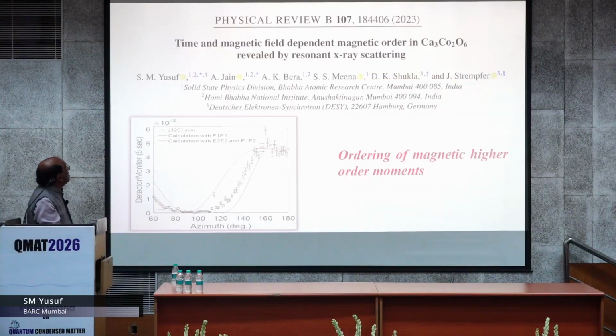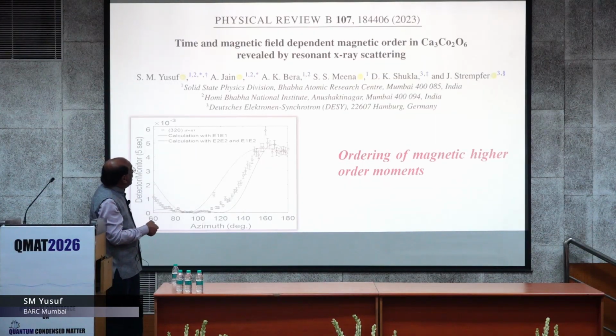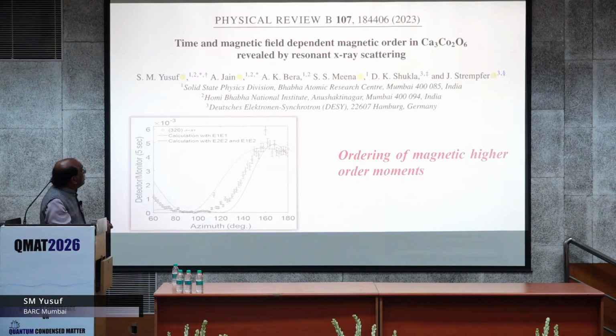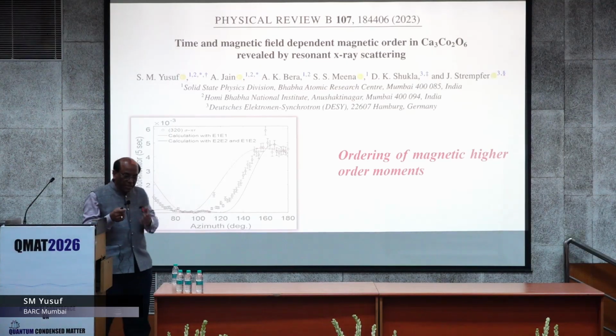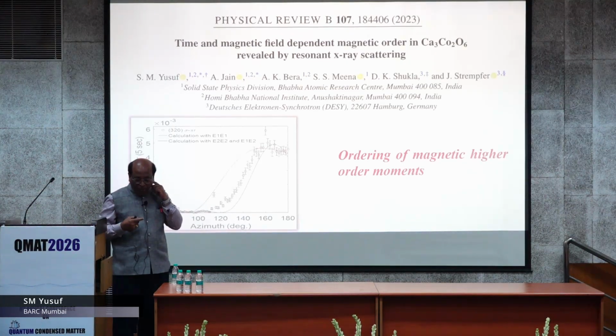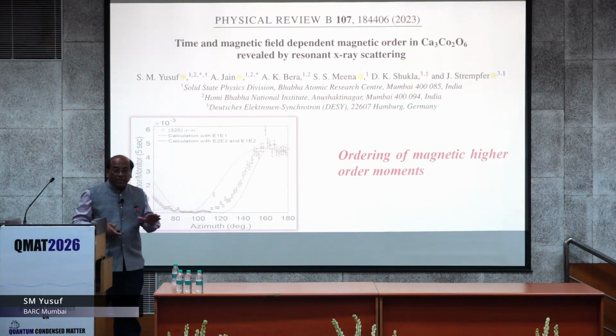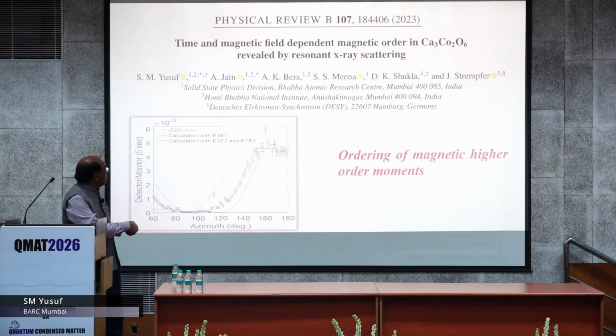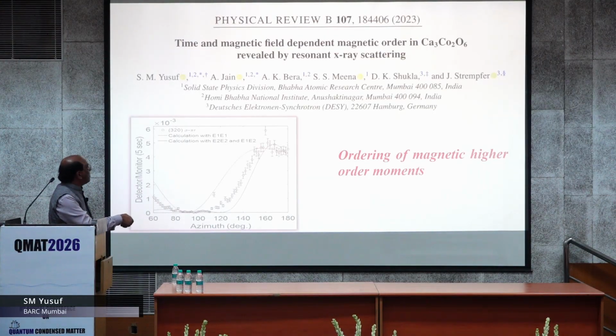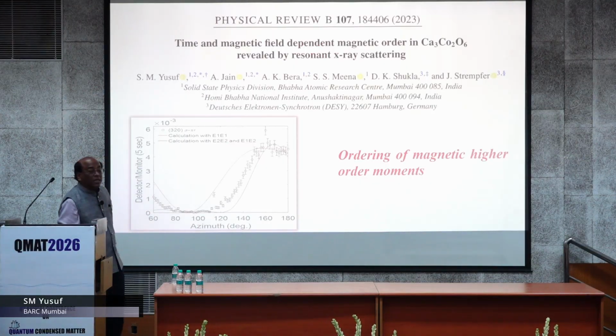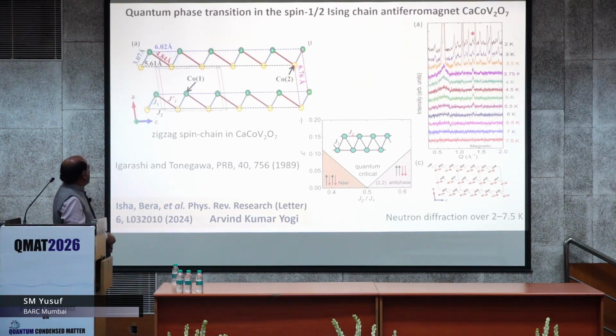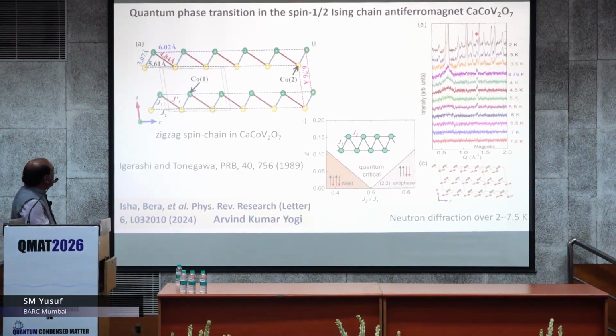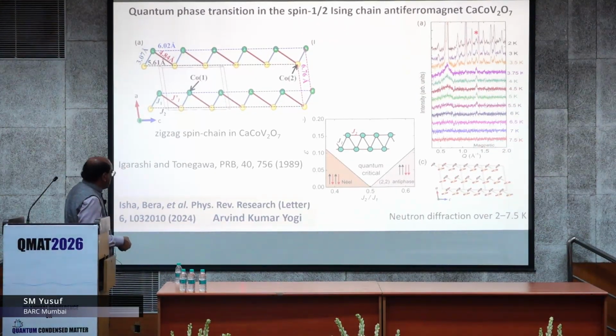So true paramagnetism is not there in this case over the temperature scale. This is yet another relatively recent study by using the Spectra 3 resonant beamline, X-ray resonance scattering. From that we could show that in this compound with the same triangular lattice structure, we cannot explain only with the dipole moment. See, whenever we talk about magnetic moments, it is understood that we are talking about magnetic dipole, right? Without saying that. So this is one example that we need to take higher order magnetic moment. Otherwise, this is my red curve, this is my experimental curve. So higher order magnetic moment presence is reflected in this resonance magnetic X-ray scattering in this fascinating triangular lattice system. Now let me move beyond that. This is yet another work, again in a collaboration with Arvind Kumar Yogi.